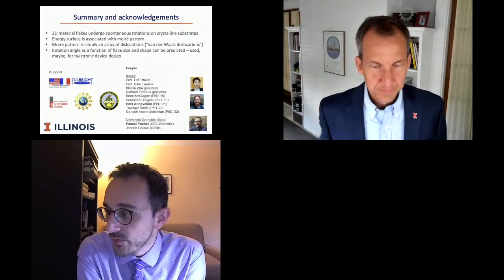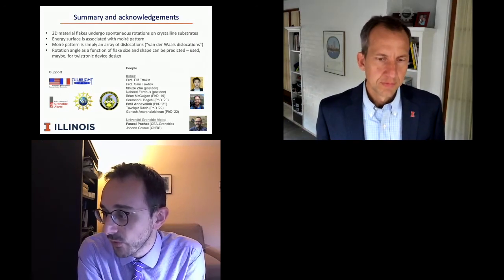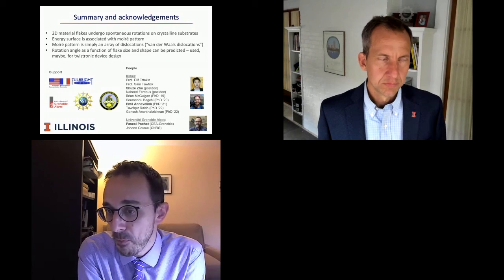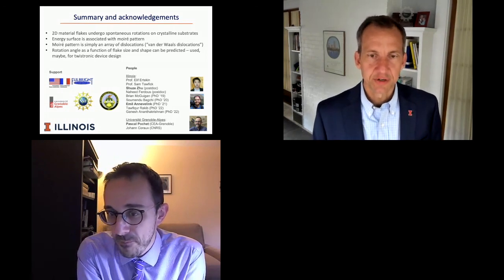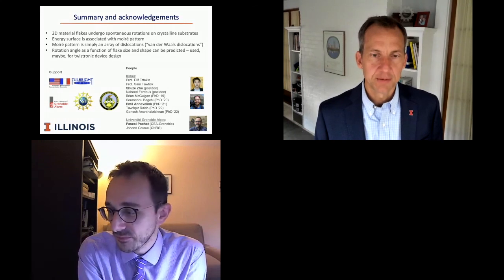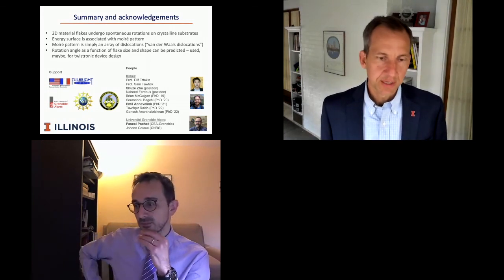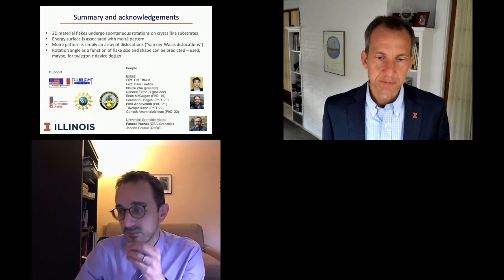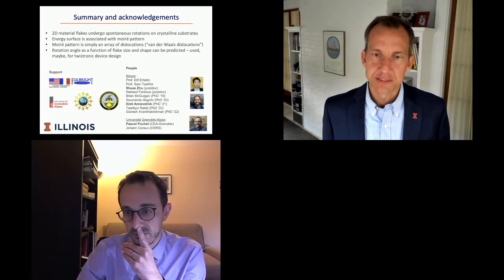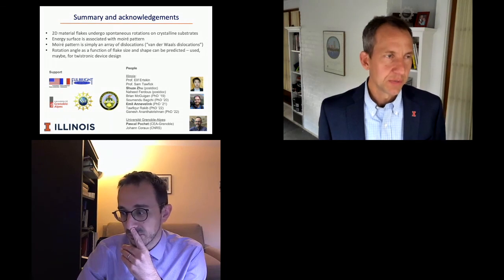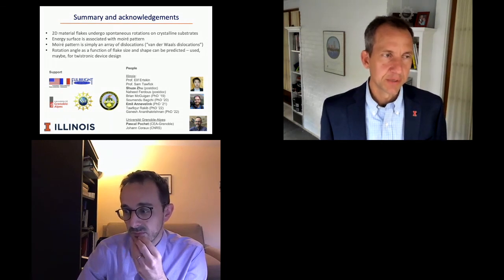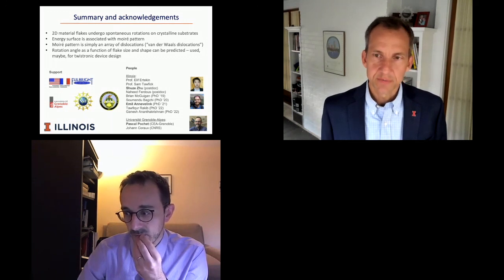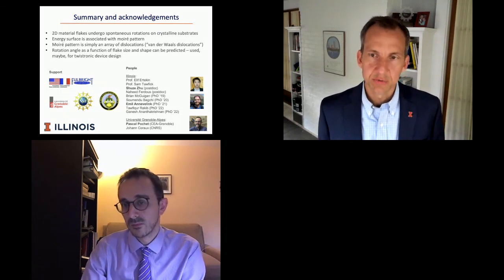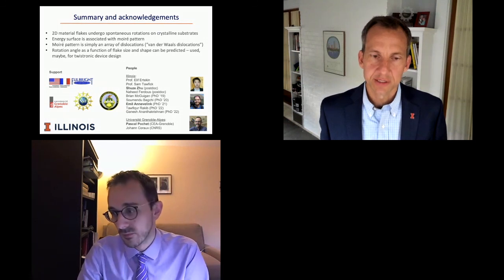I'm wondering whether you observe spontaneous rotation when you displace the flake in both clockwise and anti-clockwise directions. Okay, excellent question. Actually, that's a very good question, and I have to admit that we've not thought very much about that. But I can tell you what I expect to happen. Especially in the case of graphene, there's no broken symmetry with respect to clockwise or anti-clockwise. So you expect to see a symmetric behavior. In MoS2, depending on the substrate, you might see a small effect, because there is a kind of parity symmetry that would have to be broken. But I don't think it would actually affect the mechanics very much. It would affect the electronic structure, but not so much the mechanics. So that's a great question. Thank you.